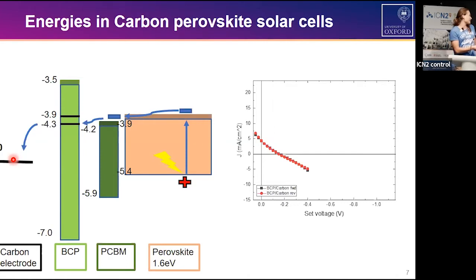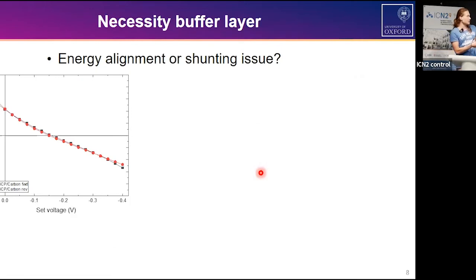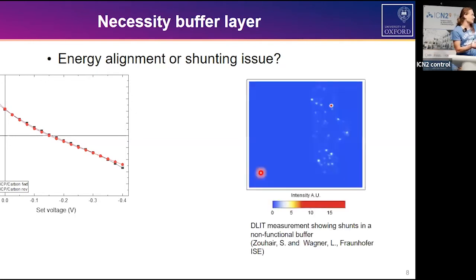But when we do exactly that, as pictured here, we get this kind of JV behavior. It looks pretty ohmic, it is pretty ohmic. It's not a solar cell at all. So for whatever reason, it is not working, and there were a lot of initial thoughts. Is it the energy alignment? Is the BCP that I use as a hole blocking layer not making a good contact to the carbon? Is the carbon destroying the stack by blade coating so much that we get shunt issues? Some of the initial data looked like we got full shunts.